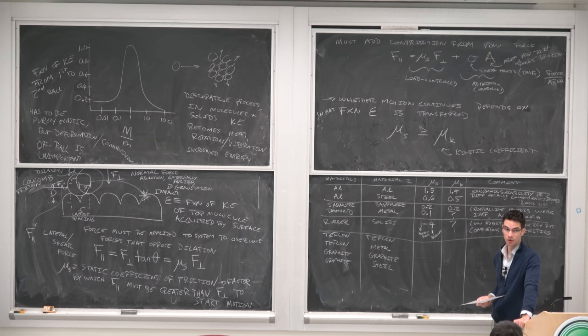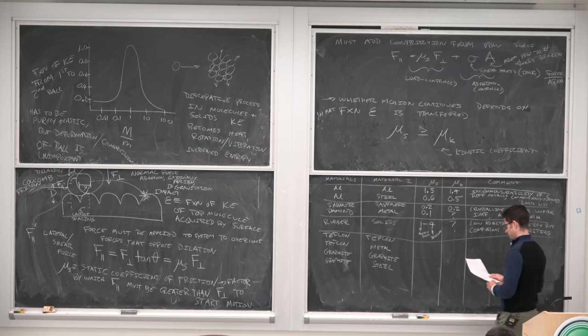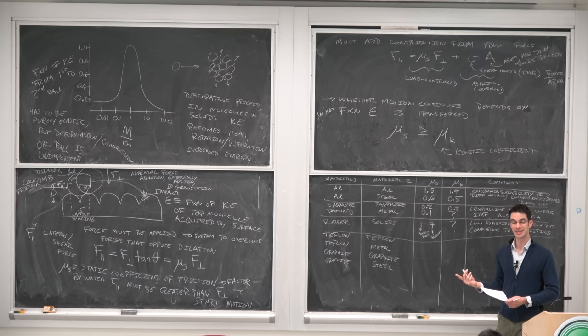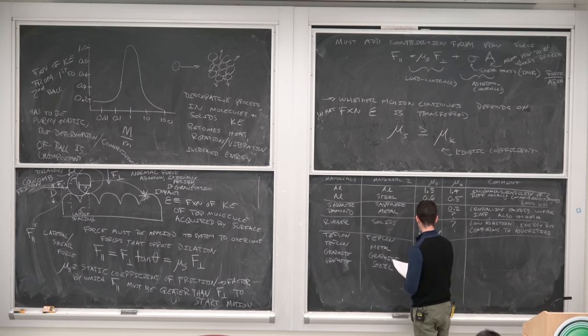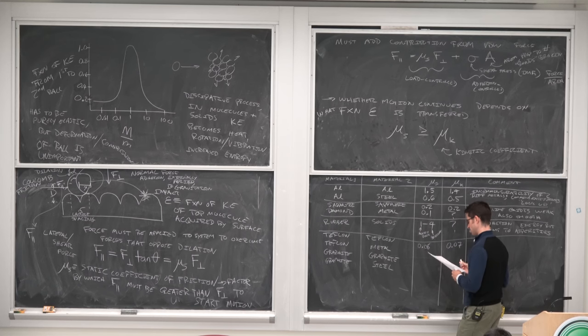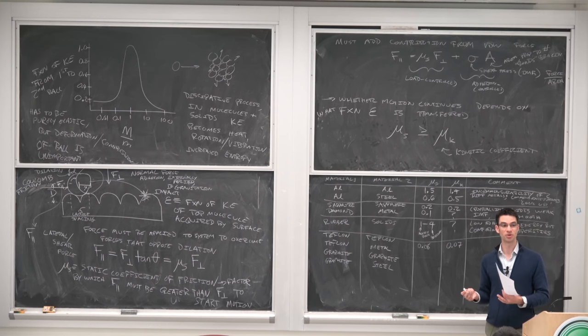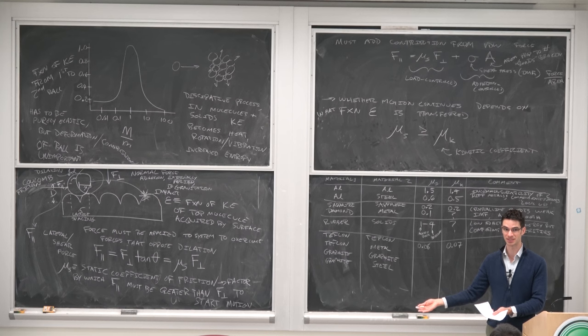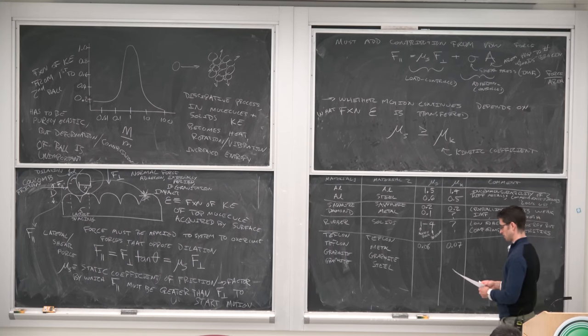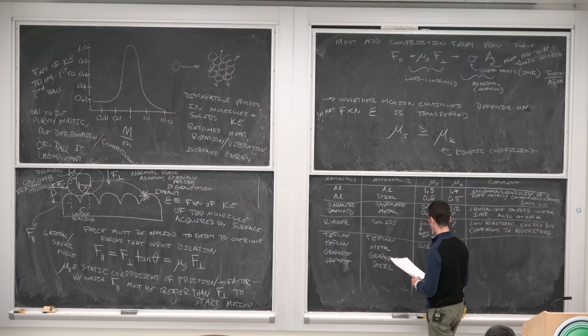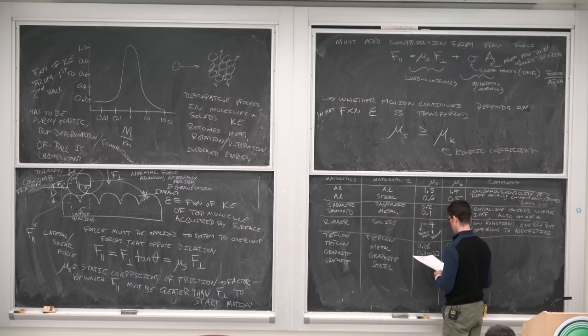So Teflon has a very low surface energy, one of the lowest surface energies of any solid material. And when it interacts with itself, because it has such a low surface energy, we have 0.08, 0.08, and 0.07. Teflon also has poor cohesion between Teflon chains. So Teflon chains will peel off of a surface and deposit on another surface. And Teflon is often used for lubrication between joints for this purpose. And if we have Teflon on metal, some of the Teflon will come off and actually still give you a fairly friction-free surface, 0.1 to 0.3.